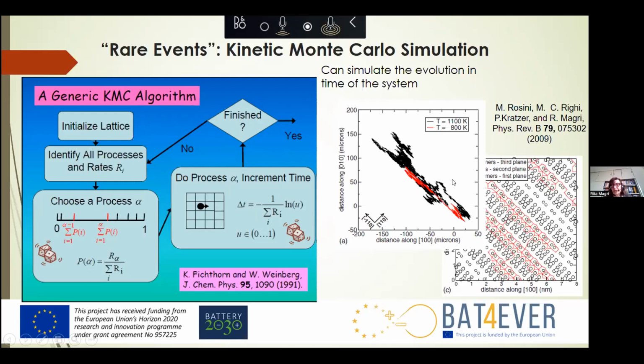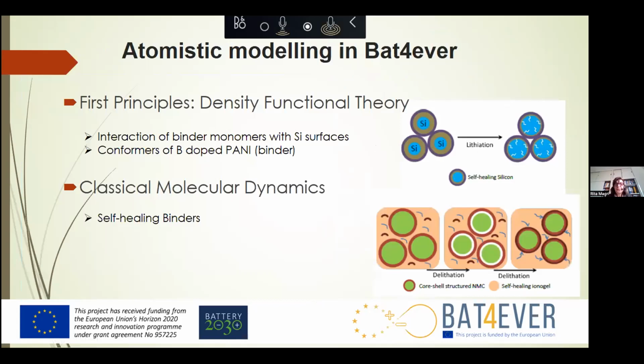Using this method, we have, for example, studied the diffusion of an atom on a surface. And we can see from these results that the diffusion of an atom on this particular surface is not isotropic, but develops mainly along well-defined directions. So this is what you can do with calculating energy, calculating activation energies and studying also diffusion of lithium atoms in the systems.